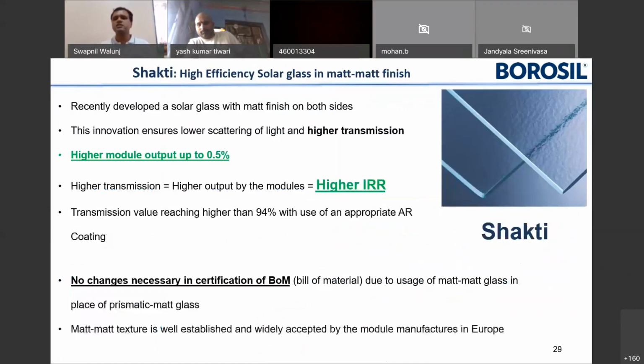This is the Shakti glass that we have developed with a pattern which is plain or matte on both sides. Because of that, the scattering effect has been minimized, and you are able to get a higher module output, at least by up to 0.5%. Needless to say, higher transmission leads to higher output and higher IRR for the developers. And also the modules are rated higher, so there are higher returns to the module manufacturers also.